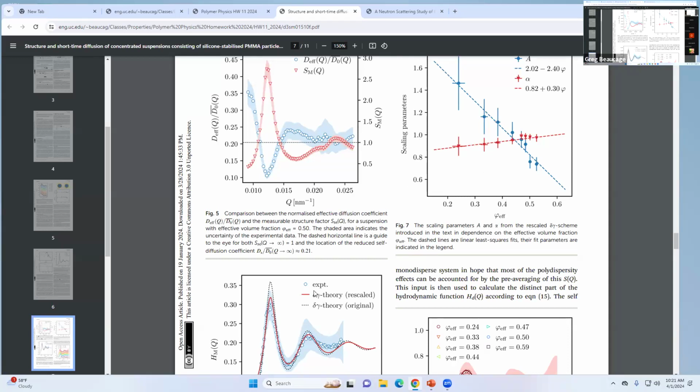And then he's also got this problem that the dashed line is a little bit off from that peak. This happens a lot with correlation functions. You have your model and then something happens to the second order peak, it doesn't match. So if you did a least squares fit, it would give you the wrong number. So he has to have another fudge factor that leaves this peak where it is, but shifts this peak either to the left or to the right, to a larger or smaller value.